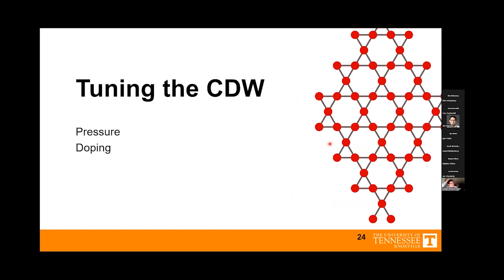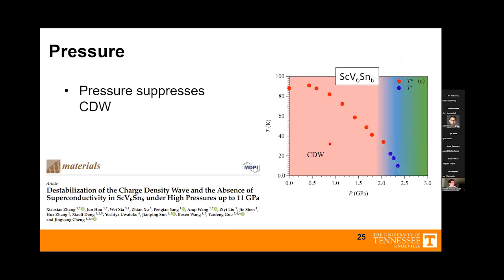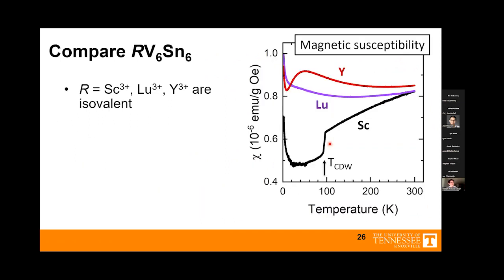So let's talk about how we set out to tune the charge density wave. Not long after we reported it, a group in China applied pressure and noticed the charge density wave was suppressed. I don't think they ever found superconductivity, but clearly squeezing this unit cell suppresses our charge density wave. And now we look at the other members of this family. Scandium, lutetium, and yttrium are all 3+ cations. So wouldn't we expect them to do the same things electronically?